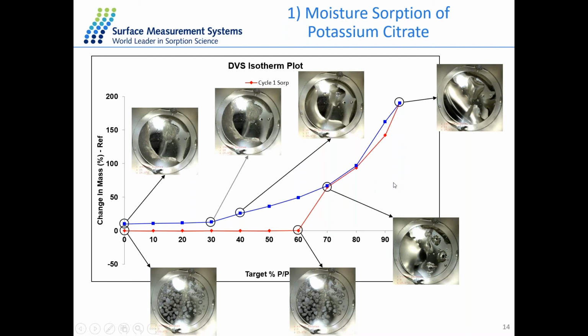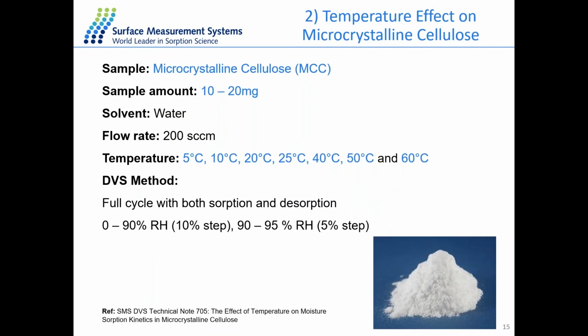So that's the example about the potassium citrate. We also have an example with the microcrystalline cellulose, and this time we would like to study the temperature effect on the moisture content of this microcrystalline cellulose sample. So we use around 10 to 20 milligrams of MCC sample, and we perform the same water sorption experiment from 0 to 95% RH at different temperatures, from 5 to 60 degrees.